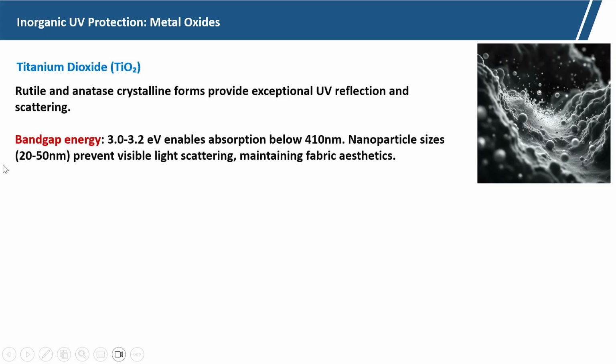The band gap energy is 3 to 3.2 electron volt, which enables absorption below 410 nanometer. So, it can get absorbed due to this band energy.